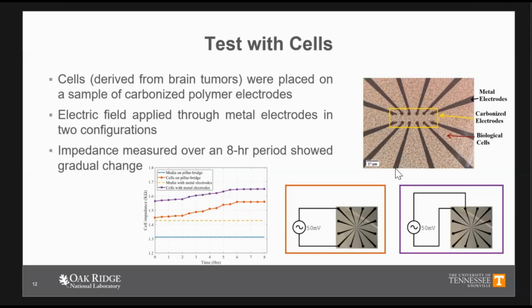And then as we apply cells in there, we get two different plots of the impedance increasing as the cells settle down and start multiplying over time. Once they settle down and start to grow, you can see over an 8-hour period there is an increase of impedance.